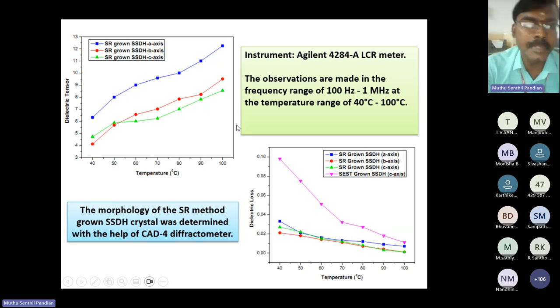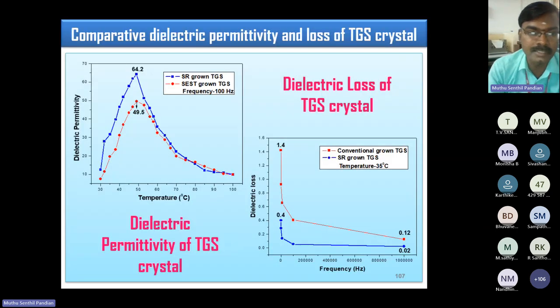So higher dielectric permittivity and a lower dielectric loss clearly indicate that the crystalline perfection and optical quality of this SR method grown crystal is superior compared to the small size single crystal grown by the conventional method. So this is that TGS single crystal.